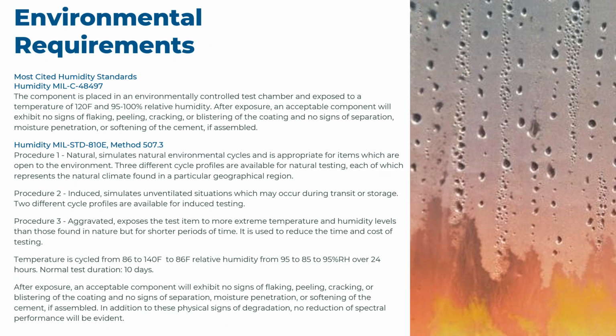Another standard, and this one actually gets progressively more aggressive, is MIL-STD-810E, method 507.3. There are 3 different procedures: natural, induced, and aggravated. Most coatings fall into procedure 1, sometimes procedure 2. With IR optics or optics used in extremely challenging environments, you'd probably want to opt for procedure 3. The cycling, again, is 86 Fahrenheit to 140 Fahrenheit, and relative humidity 95 to 85%. The duration on this is usually 10 days in the aggravated exposure mode.